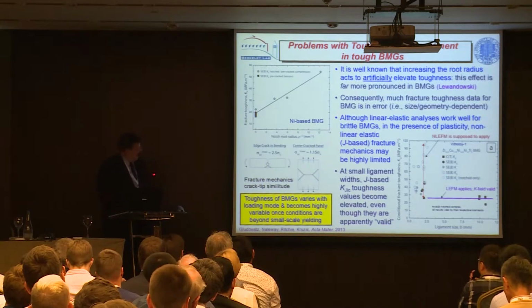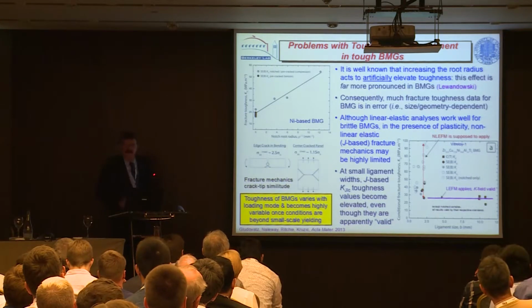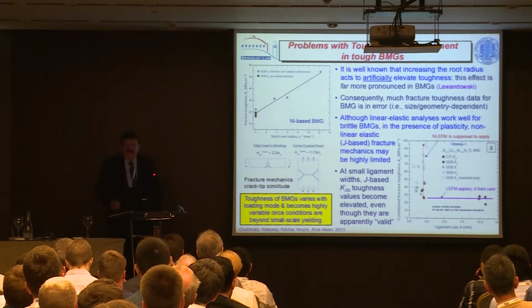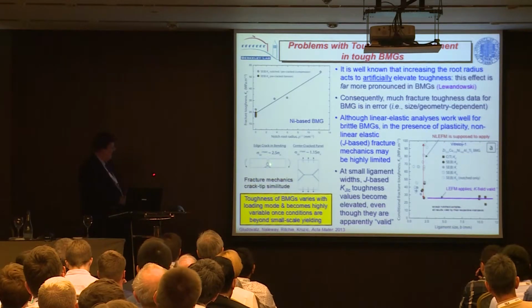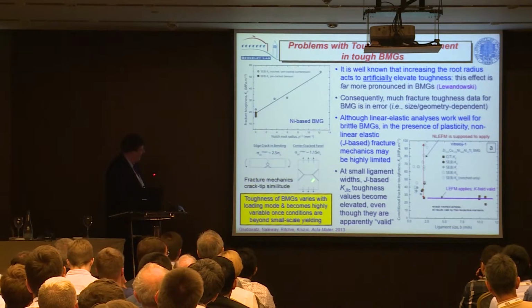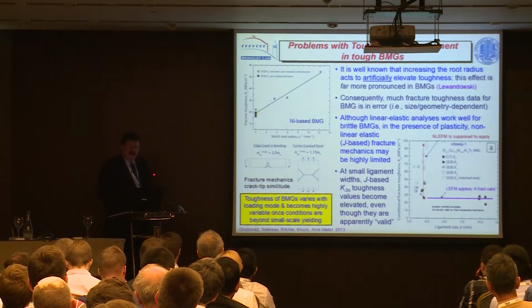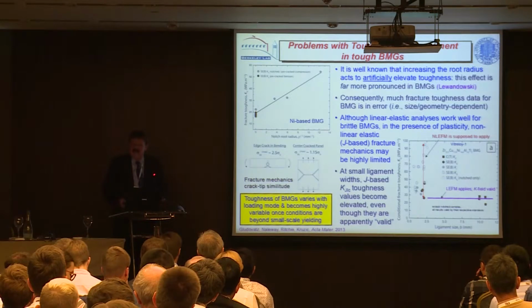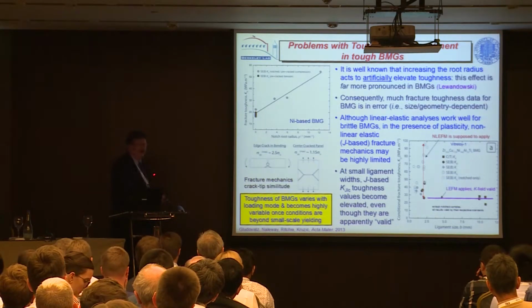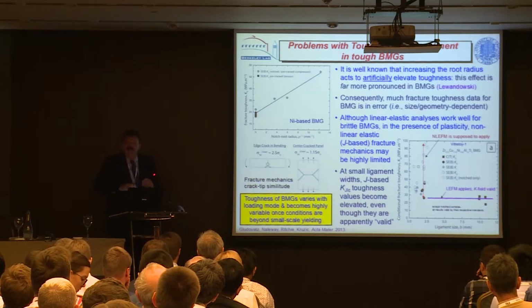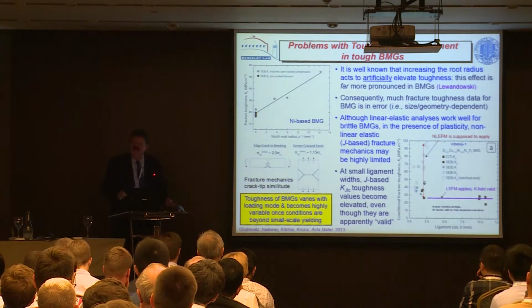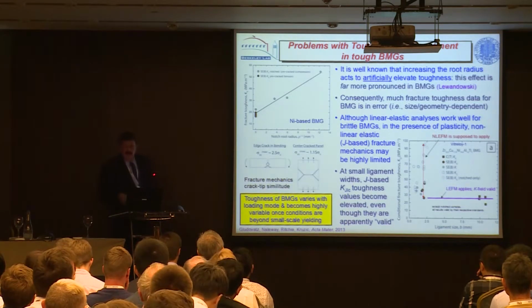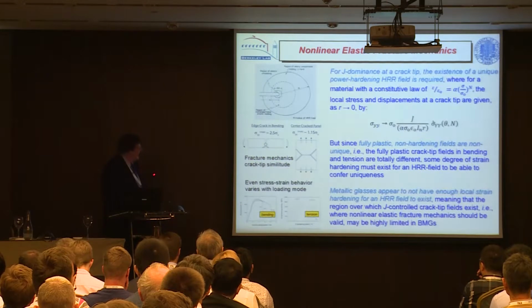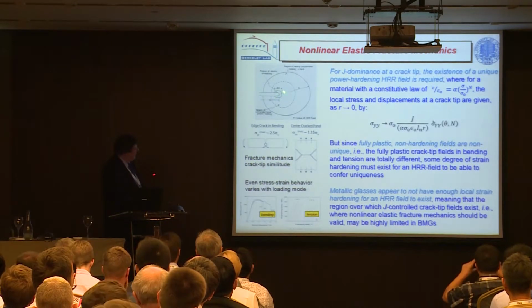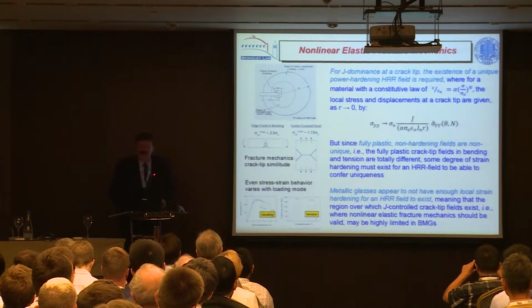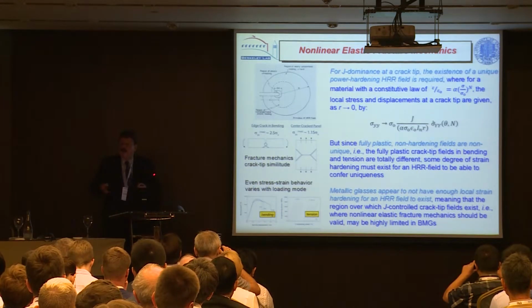Now, why is this? Well, this to me is very similar to the old story when J was first developed. We have John Landes here. He did this. They were interested in looking at two very extreme geometries, the so-called center tension versus the edge crack bending. These fields are unique under linear elasticity, but if you're in slip-line fields for non-hardening plasticity, they're completely non-unique. And the reason that J works as a means of measuring beyond the linear elastic regime is that locally at the crack tip, you get this so-called HRR field, which is a power-hardening field, which gives you some uniqueness.